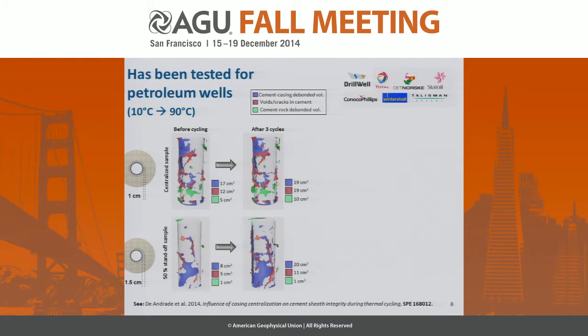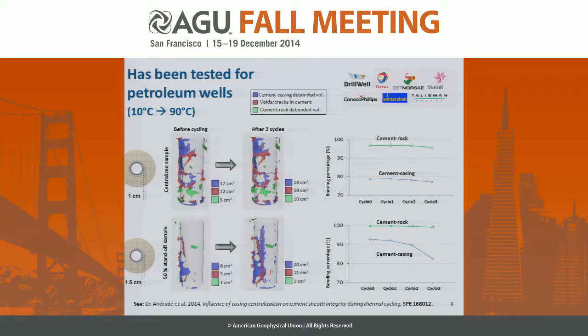While for the off-centered casing, you can actually see that a crack is developing in the sample. So this crack was on the thin side of the cement. So here you have a 50% casing offset. And then you can, of course, plot how this debonding is varying with each cycle. Here you see the 3 first cycles where little is going on in the centralized sample, and where you see quite a lot going on in the off-centered sample.